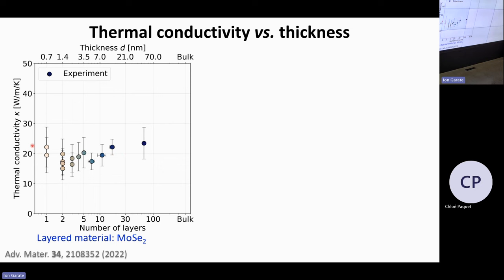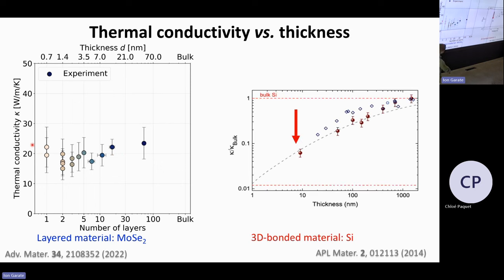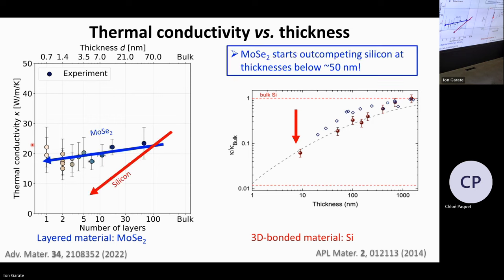So very different behavior compared to graphene, where we saw a drop of more than an order of magnitude, even for a thickness of 10 nanometers. We can go down to a thickness that is below a nanometer. This is just 6 angstroms, the monolayer case. So what actually happens is that we start outcompeting silicon below a thickness of around 50 nanometers.